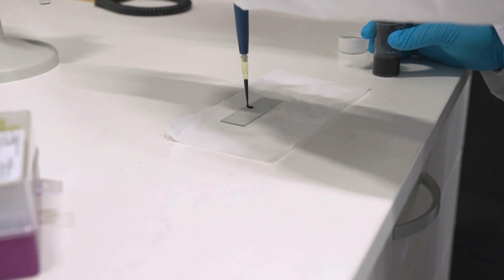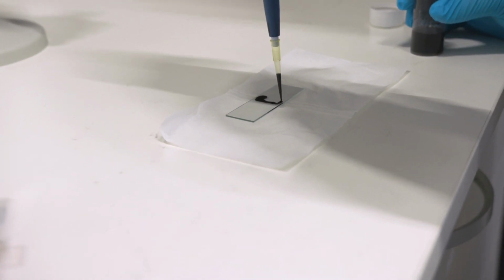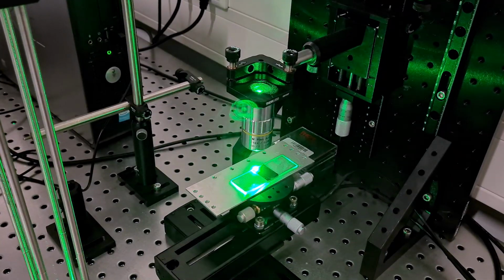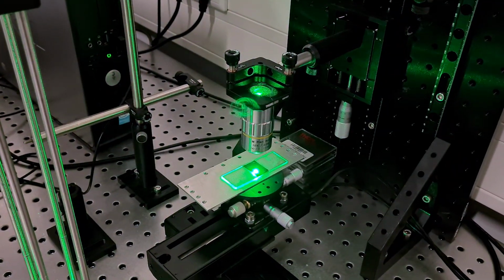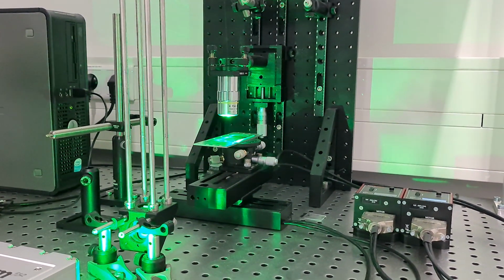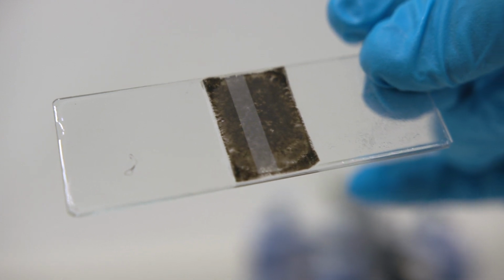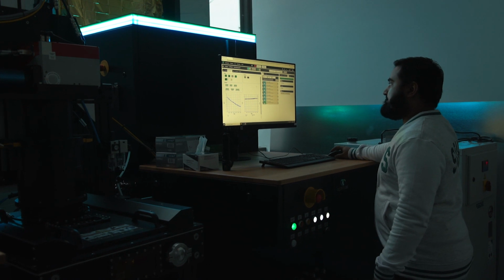The generated nanoparticles are first used to produce nanoparticle ink, which is then dispersed on the glass substrate and sintered using a continuous wave laser. The direct writing employing a continuous wave laser can be used to produce 2D magnetocaloric custom structures with micrometric resolution. Additionally, these magnetocaloric nanoparticles can be used to generate 3D structures using, for example, the laser powder bed fusion process where layer by layer metal powders can be printed. In terms of applicability, they can be used to design microcoolers for heat extraction from devices such as compact high-performance laptops, smartwatches, and minuscule sensors where heat extraction is really difficult due to their compact size.